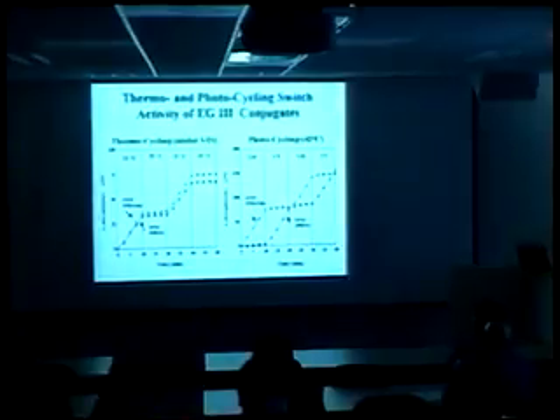And in terms of the reversibility then and the cyclability, these are also really beautiful and much better than anything we ever saw with Streptavidin. So if we look at thermocycling first, what we're plotting here is total product accumulation as a function of time. You're just sitting there with a cuvette with your conjugate in there, and you switch it between 32 degrees and 52 degrees, and this is real time here on the axis, and you just switch it back and forth and measure product accumulation.